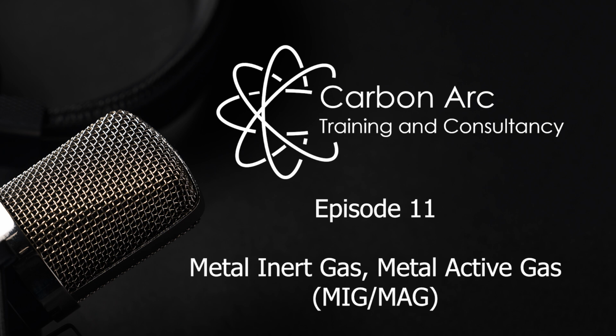Yes, globular transfer. This one is sort of the awkward middle ground between dip and spray, often occurring with pure CO2 or sometimes argon-rich gases at settings too high for dip, but not high enough for a true spray. And it's... Blobby. That's a good word for it. Large, irregular molten droplets form on the end of the wire, kind of wander around in the arc, and then detach mainly due to gravity. It's inherently unstable, produces a lot of spatter.